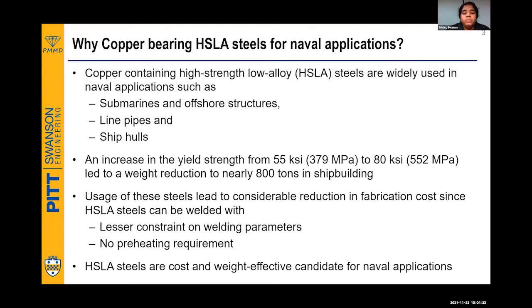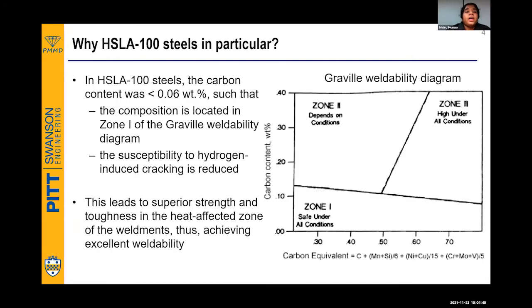In high carbon steels, the problem is you need to have preheating to reduce the cracking in the heat affected zone. Now that is what we are trying to avoid here. No preheating and lesser constraint on welding parameters.